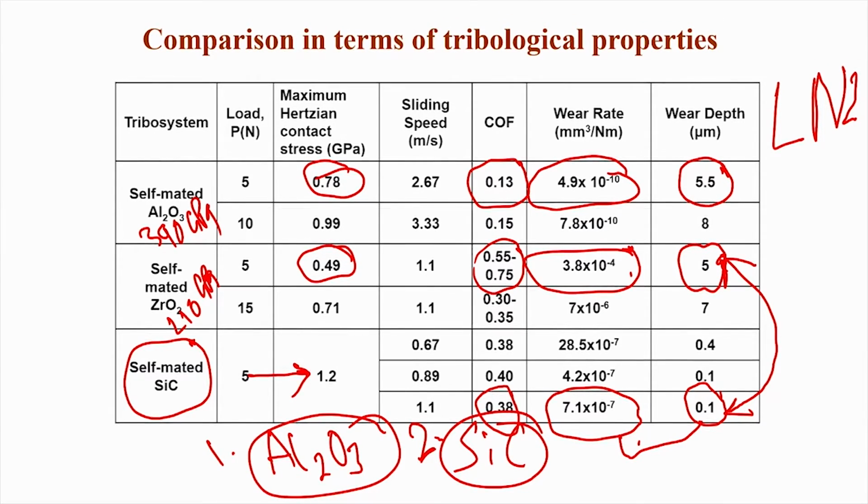In zirconia, it is transformation induced cracking. If you remember correctly, in the case of zirconia I have shown that tetragonal zirconia undergoes phase transformation to orthorhombic zirconia during the cryogenic sliding conditions. The reason I provided while explaining these intriguing observations was that in the transformation from tetragonal zirconia to monoclinic zirconia, the intermediate product is orthorhombic zirconia.